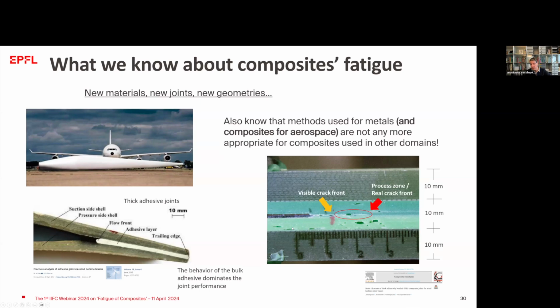Imagine in aerospace, aluminum joints with film adhesives of 1 millimeter thickness. Now we talk about joints that have 10 millimeter of thickness or even 30 millimeter of thickness. We have reports discussing 30 millimeter of thickness in wind turbines. And of course, these joints are made with very, allow me to say, primitive techniques, nothing to do with the joints in aerospace that follow specific protocols. There we have a lot of voids, a lot of manufacturing defects in the joints, and the idea is to guarantee the lifetime of a huge structure like a composite rotor blade, having in the body joints like that.